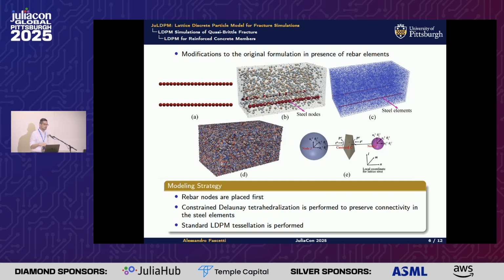And so in order to do this, we devised this technique, which is slightly different from what is traditionally done. We do this as follows. We first place the nodes that pertain to rebar in the domain, as you see here, which effectively mimics how you cast the models, because you first lay rebar and then you pour your concrete. And then we still fill the space with the polydisperse spheres, exact same, but now you have to use a constrained Delaunay tetrahedralization to make sure that your rebar nodes are still connected by the Delaunay, as you see here. And so you get this, again, very dense network of 1D elements, and then we restructure the entire method to understand what the interactions are between the parts.